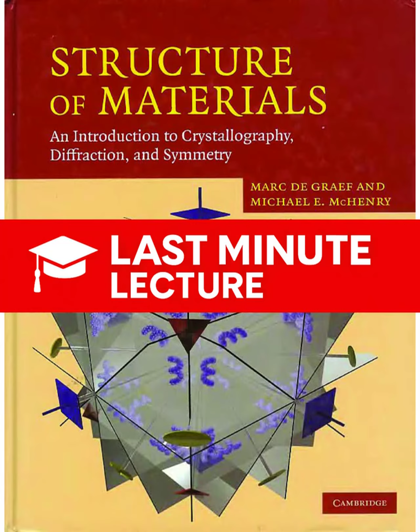Okay, beyond olivine and garnets, what other orthosilicates should we spotlight? Zircon, ZrSiO4. Definitely important, the December birthstone. Zircon is another great example where the isolated SiO4 4- tetrahedra are linked by large polyhedra. In this case, it's zirconium occupying a dodecahedral polyhedron. Right. And while it's incredibly dense, the structure is surprisingly easy to break compared to, say, diamond. It shows that symmetry and density don't always guarantee ultimate strength.